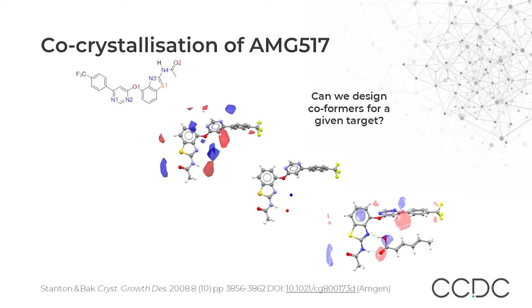A more solid example of co-crystallization is the Amgen molecule shown here on the screen. It was observed to have problematic solubility — it was highly insoluble in water — and co-crystals were a way of modifying the physicochemical properties, in particular solubility. The full interaction maps can be used to help with co-former design through hotspot analysis, checking which co-former would satisfy interactions in the suggested hotspots. The sorbic acid form has high aqueous solubility, and it does form interactions exactly where the interaction maps suggest. More details are linked in the paper shown at the bottom of the screen.